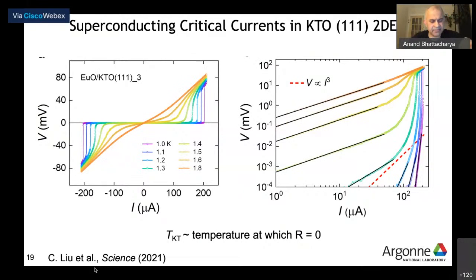More evidence for the same is found in measurements of critical current. I should mention there are some constraints here. The critical currents are actually very high, and we are not able to determine how high they are because our fridge wiring will not hold up if we drive that current through, the fridge won't cool anymore. And there are problems.